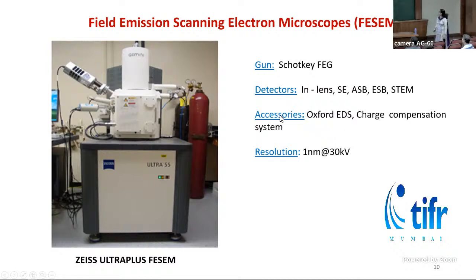Now, why is a charge compensation system needed? Earlier, I mentioned that we need conducting samples to be imaged with SEM. What happens is when this electron beam hits the sample, the secondary electrons emitted from the sample, if they're not grounded properly, create an electron cloud over the sample. And that electron cloud deflects the primary beam, resulting in movement of the image, or some portions of the image getting dark, or some portions getting excessively bright.